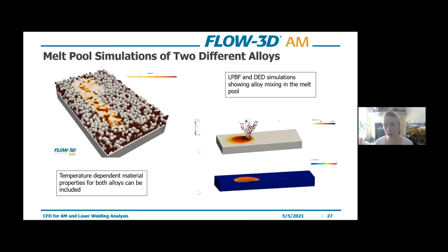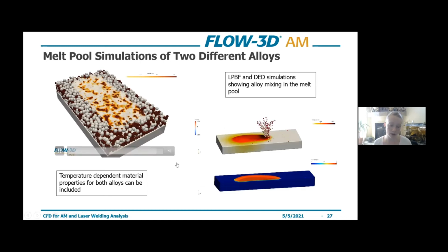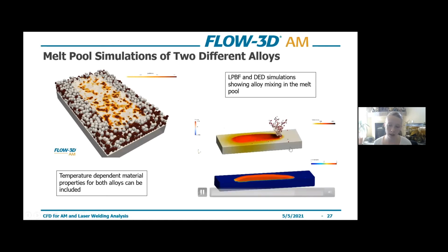So all of their thermophysical properties are independently defined, surface tension values independently defined. And there's different ways we can approach this. So laser powder bed fusion example here on the left, we have evenly mixed copper aluminum alloys, and then we're just melting them. In a directed energy deposition where we have a powder or a wire feed that's being deposited onto a substrate, we can model mixed powder in the powder feed. We can look at having a different material as the substrate versus the powder feed, say if you're doing repair work in a cladding setting or something to that effect. So there's a lot of different ways that you can employ the 2 materials, but being able to capture their effects independently as they're joined together is extremely useful.